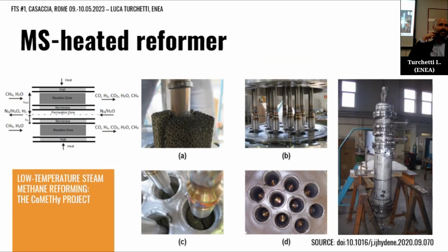But probably this is clearer if we see these pictures of the reactor before being installed in the plant and being, of course, covered with insulation, which wouldn't allow us to understand what this system looks like. So here you see the reaction tubes. This is the tube sheet basically of the system. What you see here is the membrane, which is a tubular membrane, and what you see here is the catalyst, which is a monolithic catalyst deposited over a silicon carbide foam, which ensures activity of the catalyst, and also ensures good heat transfer properties across the reactor bed.